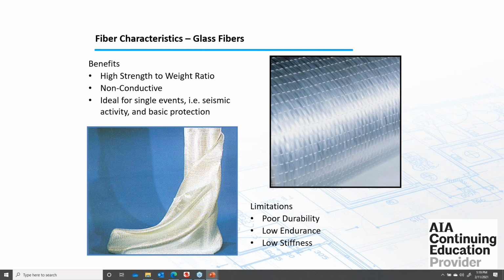For the glass, again, it's also very, very high strength, especially for its weight. But it's about half as strong as the carbon. But the big thing with the glass is it's non-conductive, so we can use it as an insulating layer in those situations that I just described if we need to. It gets used primarily for single events like a seismic event, an earthquake, where it's just going to take the load, and then after the event, you can go and inspect it, see if it's damaged at all, if it needs to be repaired before it gets another earthquake.